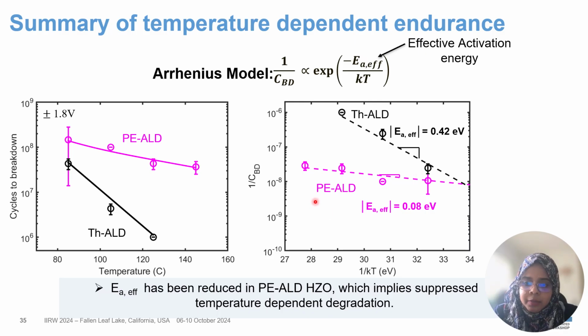So here we see that in the plasma ALD device we are having lower effective activation energy compared to the thermal ALD sample. What this tells us is that in our plasma ALD device we are having suppressed temperature dependent degradation.